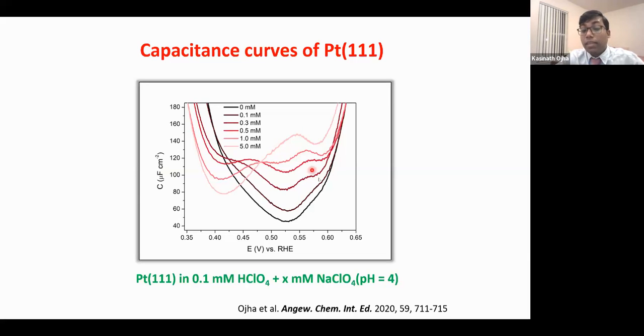Dr. Kashinath, what about the minima at 0.45, between 0.4 and 0.45? Yeah, you talk about this one. This is not a capacitance minimum. There is specific adsorption happening right here. I told you the hydrogen adsorption region. So this region is where specific adsorption is happening, and that overlaps with the double layer region. So there it's creating a minima, but this is not actually a minimum in the capacitance. This is a mix of capacitance and specific adsorption. Same as here, but those are not really minima to consider.